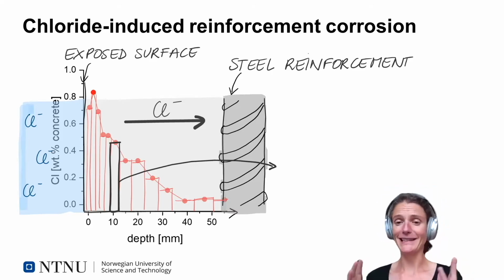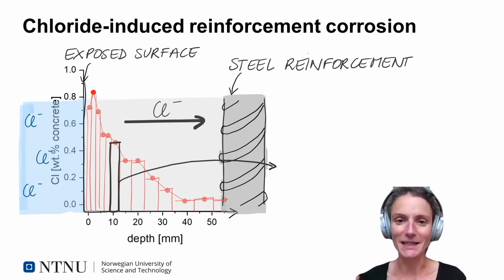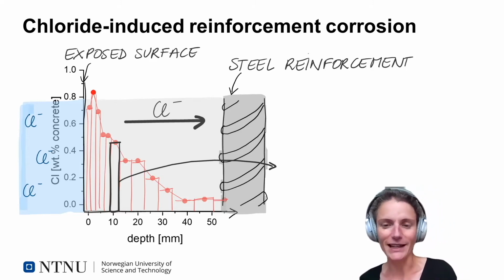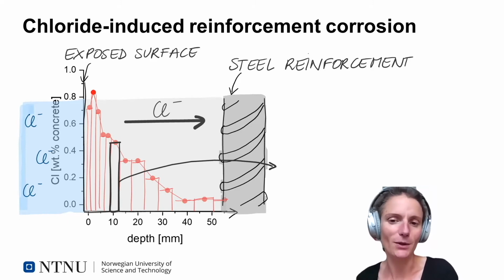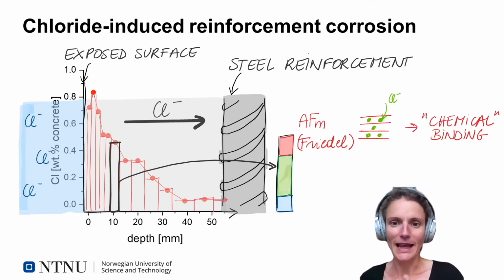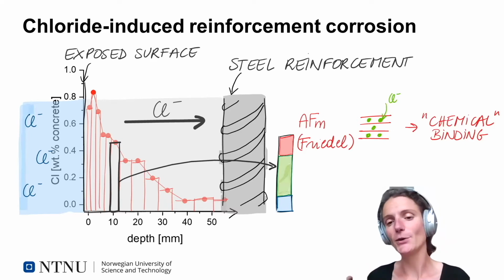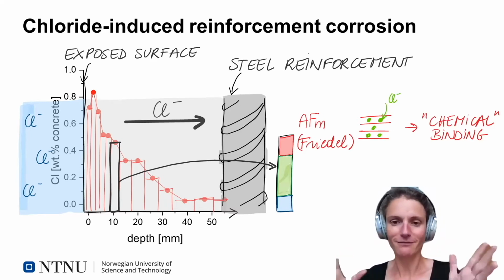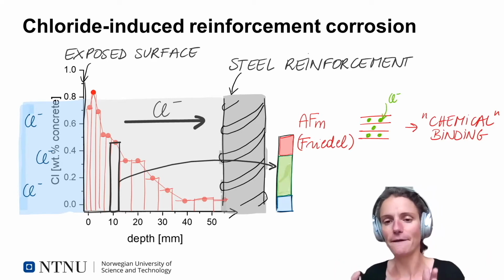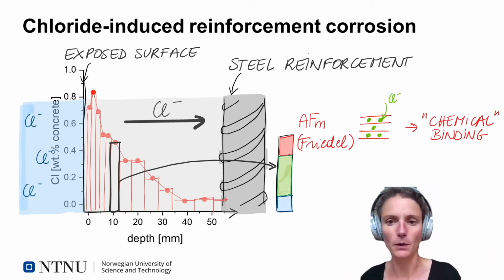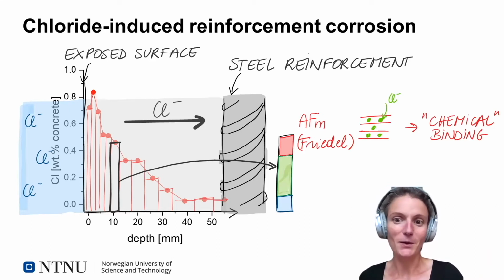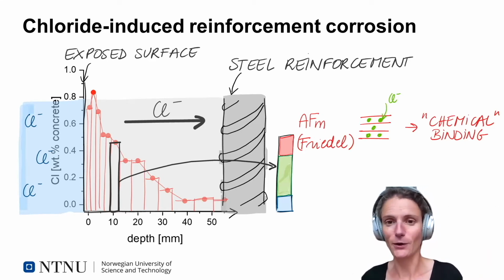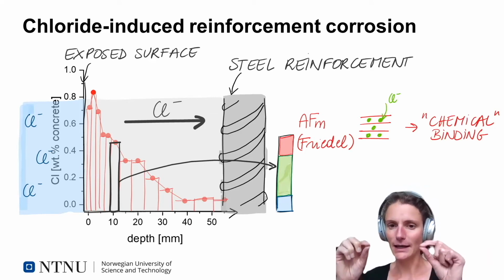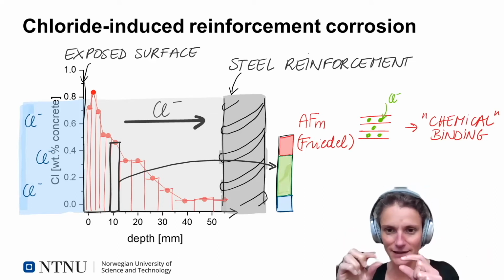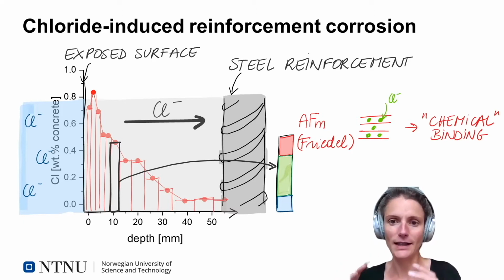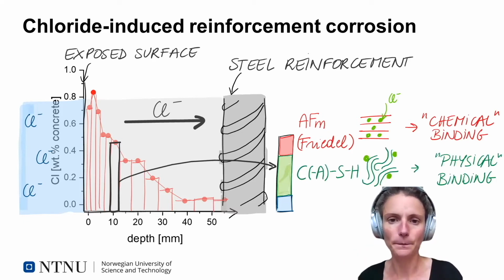When we talk about chloride binding in concrete, we're actually talking about chloride binding in cement paste, because we consider the aggregates as a non-reactive part when it comes to chlorides. So in the cement paste, we have specific hydrates that are known to be able to take up chlorides. And one family of them is the AFm hydrates, so the aluminate ferrite monosulfate hydrates. One of the most known ones is Friedel's salt, the chloride-containing AFm. And the chloride is there taken up in the crystal structure. It's actually in the interlayer. So it's part of the structure, and that's why we call this chemical binding.